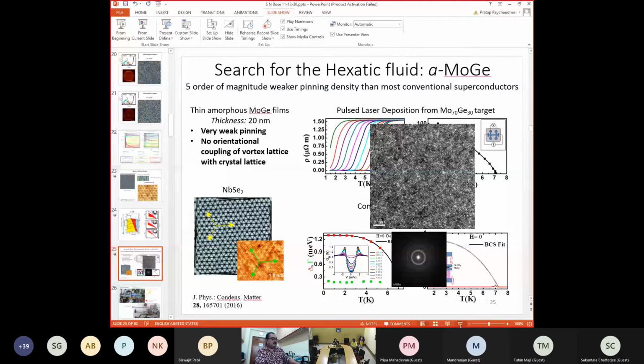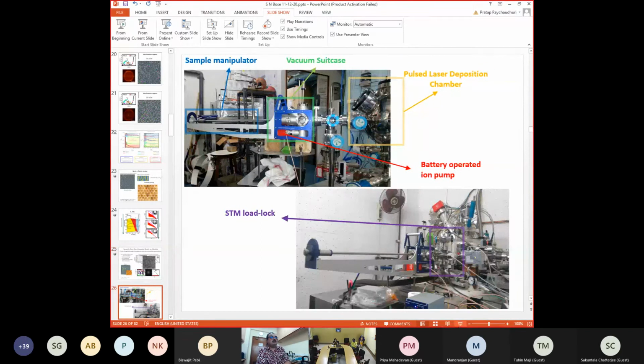So we use this technique where we have an ultra-high vacuum suitcase. We grow this in this pulse laser deposition chamber, and then with this manipulator, we take the sample into this ultra-high vacuum suitcase where it is kept at 10 to the power minus 10 torr. Then we can disengage it, connect it to the STM, and then it goes straight into the high vacuum, low temperature STM without having ever been exposed to air.